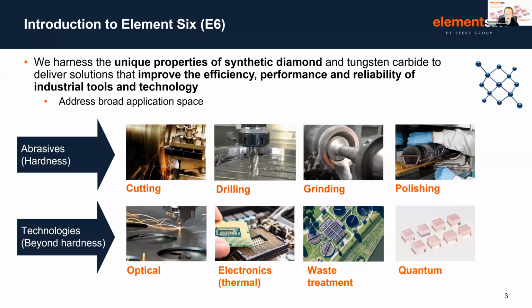So traditionally, one of our big application areas within technologies has actually been in optical. What I have here is an optical window made of diamond. You're going to have to trust me that it's diamond and not a piece of glass, but the key difference with diamond is that we have an optical transmission window that extends from the UV into the far infrared. When you combine that with the fact that diamond has a very good thermal conductivity, it means diamond is an excellent material for modern high power infrared lasers. But given the topic today, obviously I'm going to be focusing on the emerging quantum applications using lab-grown diamond.